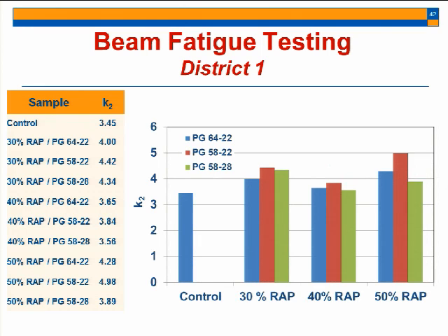But when we introduce this double bump into these mixtures, we always somehow saw a reduction in the K2 values. I may not be able to explain why this happened, but as the green ones, as you can see, all of them behave fatigue-wise less than the one with PG 58-22.